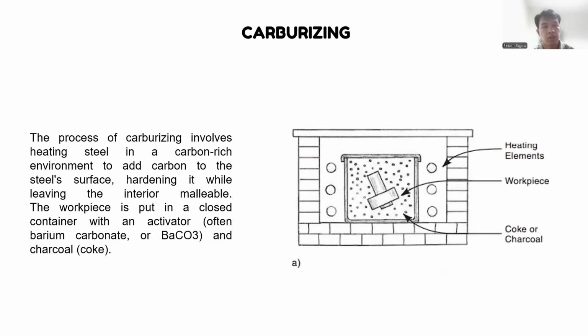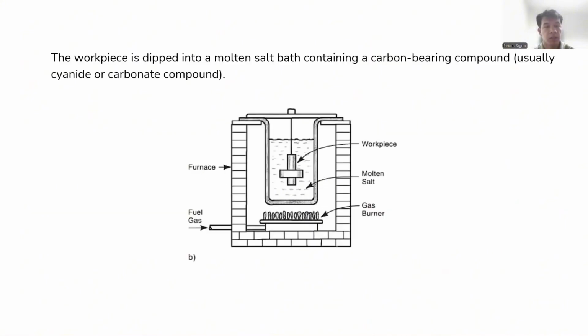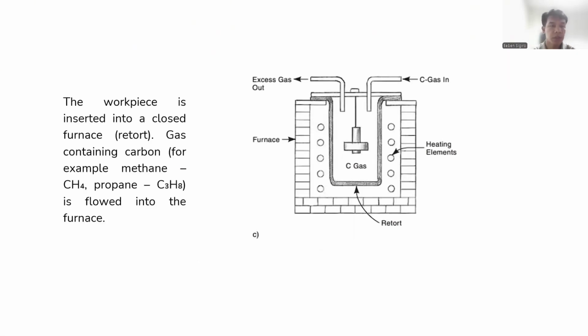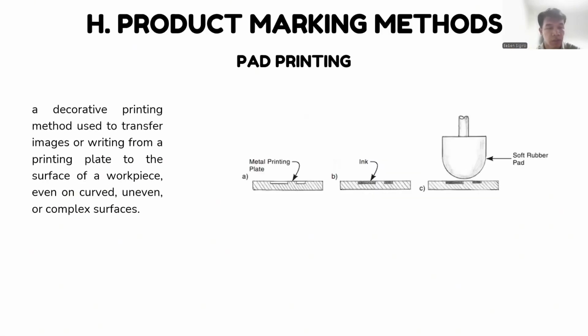Carburizing. The process of carburizing involves heating steel in a carbon-rich environment to add carbon to the steel surface, hardening it while leaving the interior malleable. The workpiece is put in a closed container with an activator. The workpiece is dipped into a molten salt bath containing a carbon-bearing compound. The workpiece is inserted into a closed furnace or retort. Gas containing carbon, for example methane, is flowed into the furnace.